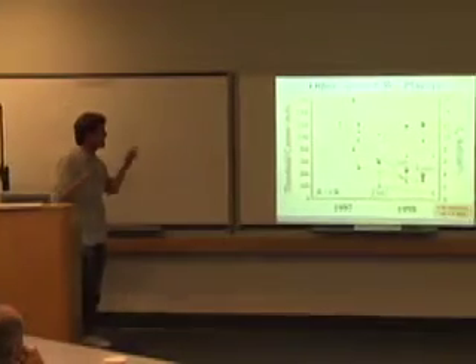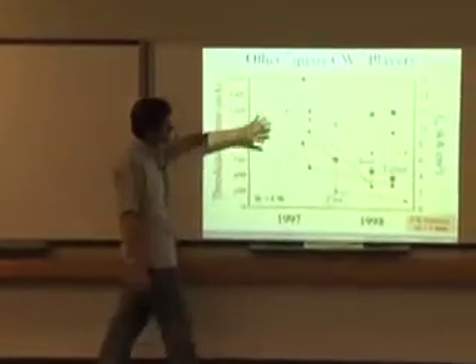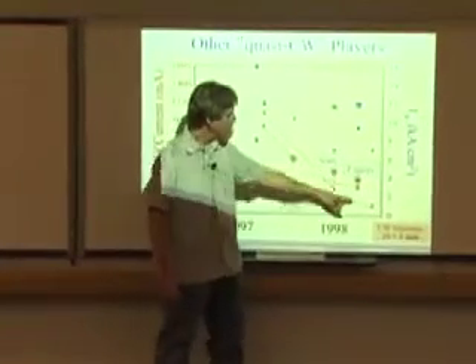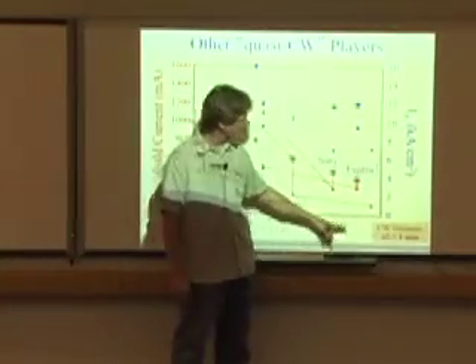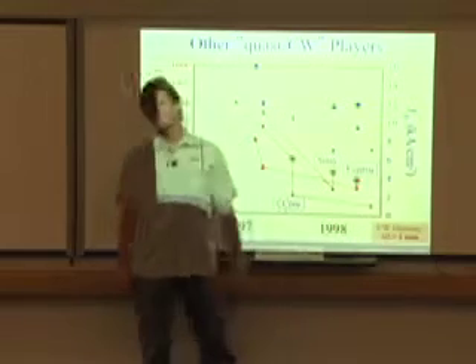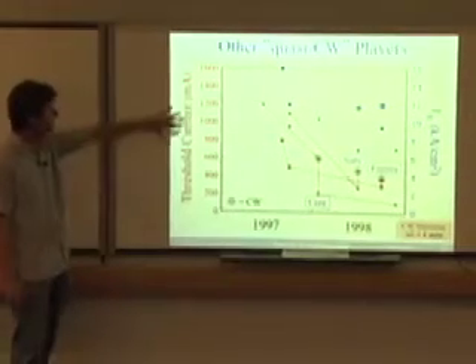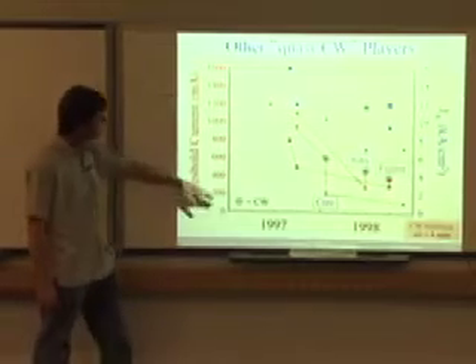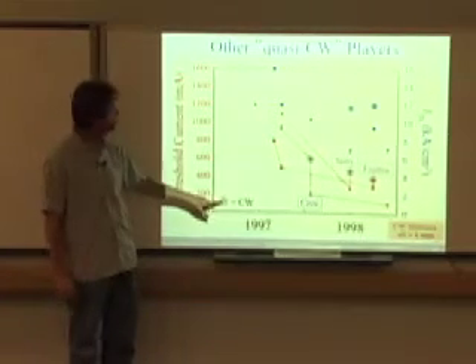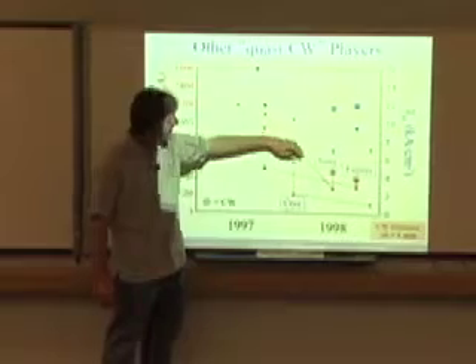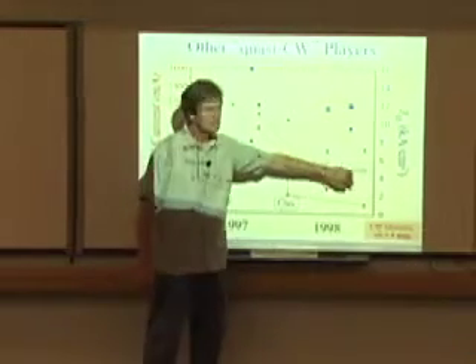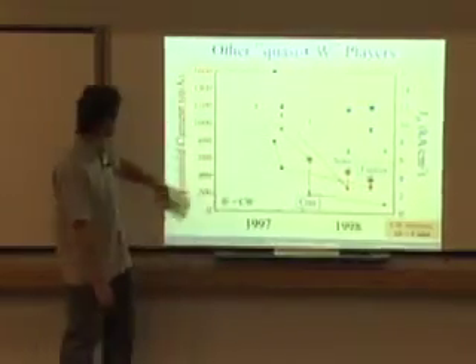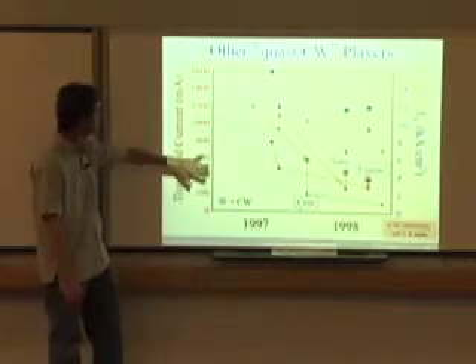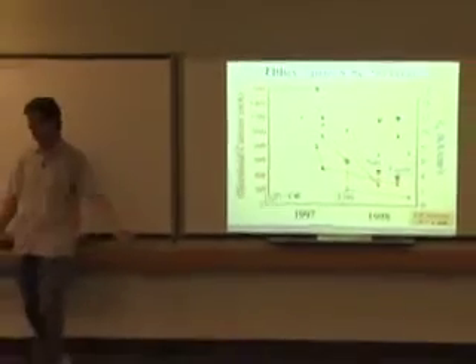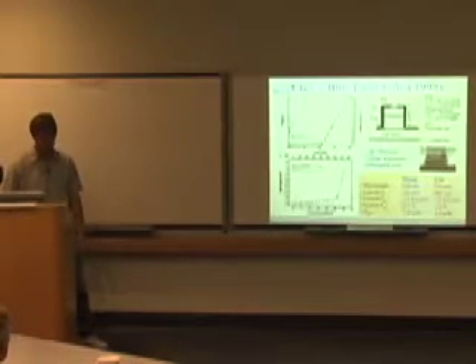Now, if you look at other quasi-CW players, and I say quasi because all of the CW lifetimes from all the other players that reported at the time, up until the end of '98, were less than a minute. We'll show what Nichia had in just a second. You see the gray circles are where CW operation was achieved by these companies. Cree got it in early '98, Sony in mid-'98, and Fujitsu near the end of '98. But again, the threshold currents at which they got CW are hundreds of milliamps. So nothing even close to what Nichia was doing.